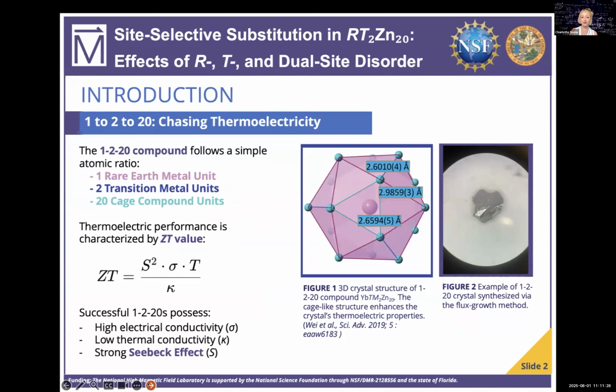And we evaluate how well these materials perform in those conditions using a number called ZT, which measures thermoelectric efficiency based on three key properties. There's high electrical conductivity, low thermal conductivity, and a strong Seebeck effect, which basically is how well that material turns heat into voltage. Our goal this summer was to improve ZT at low temperatures by tuning the chemistry of RT2 zinc 20 compounds.